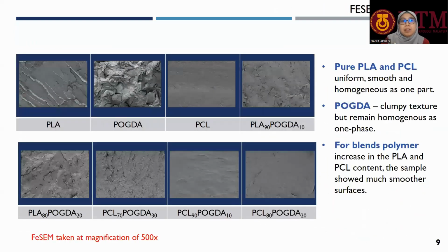Here is the FESEM morphological study on pure PLA as well as the blend. Here you see that pure PLA and pure PCL usually have a smooth surface, and POGDA here has a clumpy texture but remains homogeneous as one phase. For the blend polymer, starting from here is 90-10, 80-20, 70-30. With increasing PLA and PCL content, the sample is smoother than when POGDA is at higher content. That means if we have PLA and PCL at a higher percentage, we can get a smoother surface of the sample.